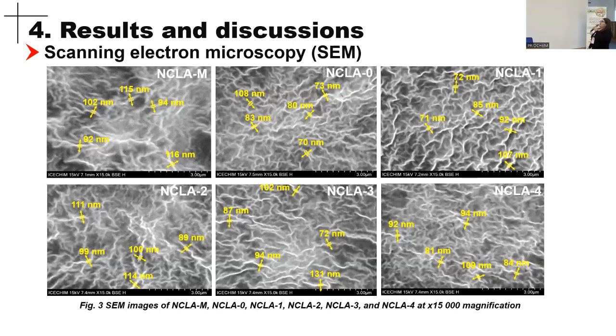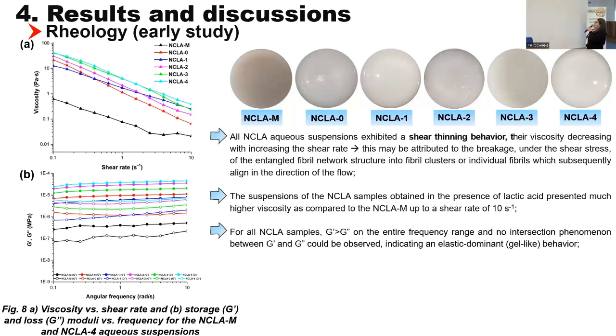So we can say that we indeed obtain cellulose nanofibers, and this also means that a fraction of the cellulose suspension suffered an advanced defibrillation, since we can see that in the case of lactic acid especially, the fibers are more individualized, while in the case of the control sample, the first picture, the fibers are more agglomerated, probably due to the hydrogen bonding interactions between the hydroxyl groups from the surface of these fibers.